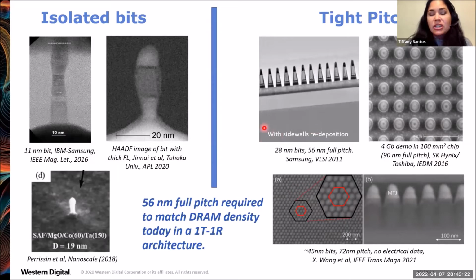Okay, and the reason why this is so challenging is because you need to etch a lot of metal to make your MRAM bits, because it's primarily a metallic multi-layer, and that metal gets redeposited on the sidewalls and will short the MgO tunnel barrier, and then you'll get no electrical data. For example, this study from Samsung, they did the tight pitch array, but with no electrical data.